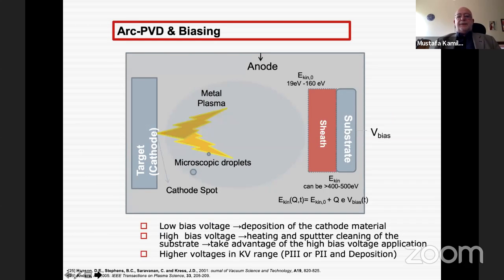So, as I told before, you can apply a negative potential to the substrate surfaces. So what does this do? It helps us to further increase the energy of the ions that are coming to the surface. Normally when we don't apply any bias voltage, the energy of the ions that are coming to the surface ranges between 19 eV and 160 eV. However, when we apply a bias voltage, then we multiply the voltage that we apply with an additional contribution, and we can increase the kinetic energy of the ions that come to the surface up to 400 to 500 eV. So that's a very high energy.